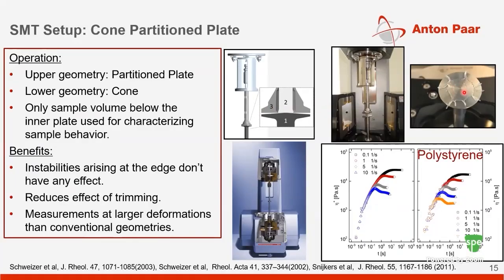Hopefully this will be clear in the bottom data slide here, where the polystyrene data was generated on a traditional cone plate versus a cone partition plate. You can see how for steady startup shear experiments, almost a factor of 10 increase in shear rate can be achieved just by using a cone partition plate. So that's another unique thing with a multi-drive device.